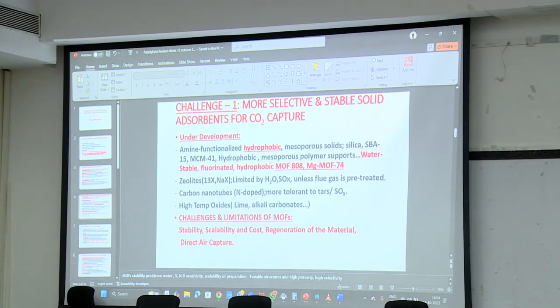But zeolites are poisoned by water. So, the regeneration of the material. And for direct air capture, you really require very high capacity for adsorption. So any breakthrough would come in solid adsorbents, maybe MOF. These are basic materials. The basic oxide will preferentially adsorb carbon dioxide because carbon dioxide is an acidic molecule. That is why magnesium, because these are basic solids which will preferentially adsorb carbon dioxide. Carbon nanotubes have been tried. They are more tolerant, but they are very expensive. In any technology, economics is the front. You should never forget it, keep it always in mind in developing any technology.